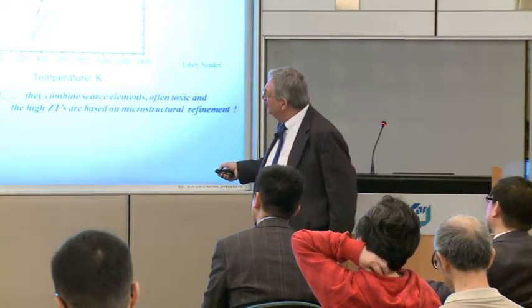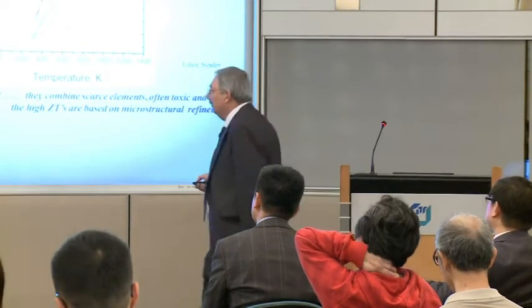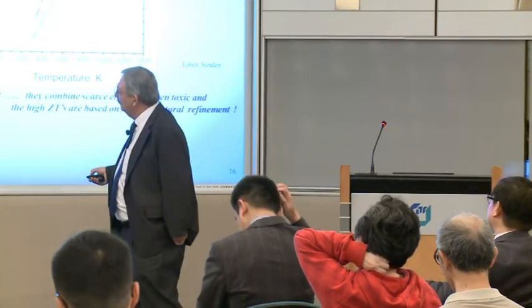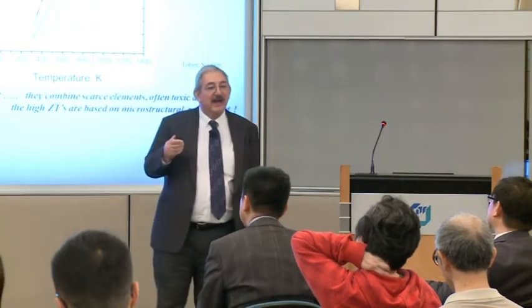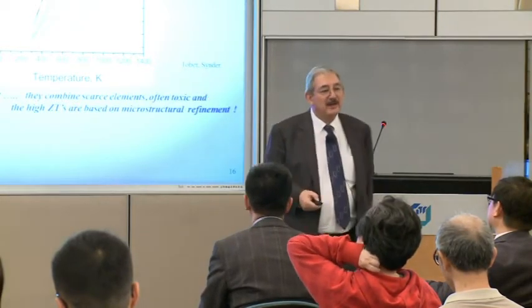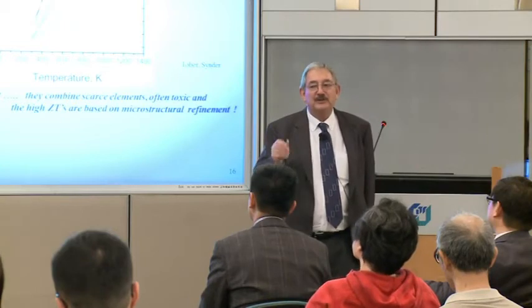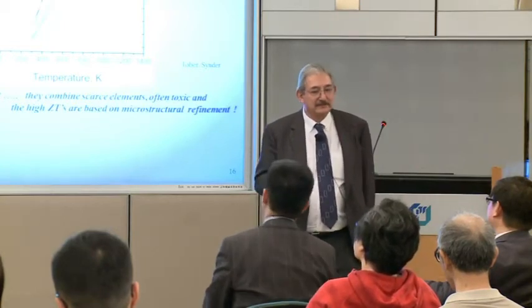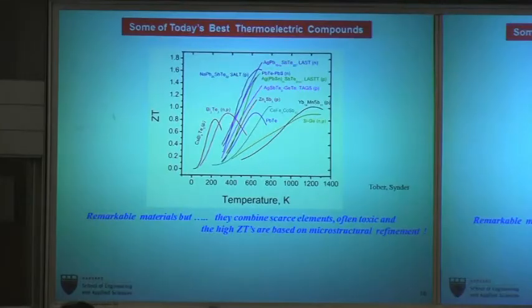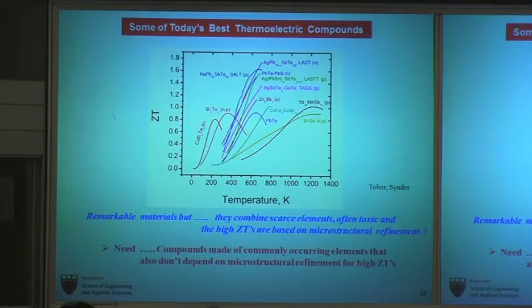So these are remarkable materials, and there's been tremendous advances for thermoelectric coolers in the development of these materials that can be used at a moderate temperature. But they're often scarce elements, they're often toxic, and the high ZTs, as I'll describe in a minute, are really due to manipulation of the microstructure. And that's important for reasons I'll describe. So what we really need, as I mentioned before, and I'll try and justify now, is compositions that are based on more common elements and that don't depend on microstructural refinement.